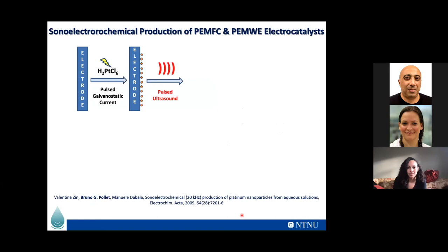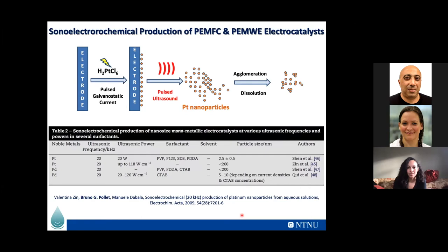You've got the potential for agglomeration and dissolution if you are not using any surfactants. These are all aqueous solutions. That could also be a big drawback. Then you could look at using different surfactants in order to separate those nanoparticles. But the problem is that it's hard to clean those nanoparticles.